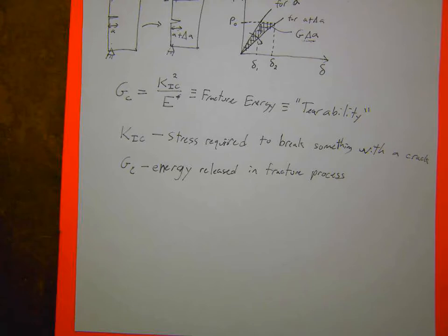But what you notice is now there's these iso lines, these dashed lines going down at a certain angle, and those iso lines should be toughness. There we go. Toughness GC, which is KIC squared over E. So along each of these dashed lines, that's a constant GC value. You can see that even though nickel alloys are one of the toughest things that we have, and the fracture toughness is orders of magnitude bigger than a rubber, if we actually look at, say, a natural rubber, it has a similar GC. So intuitively, this is how difficult it is to tear a material apart.